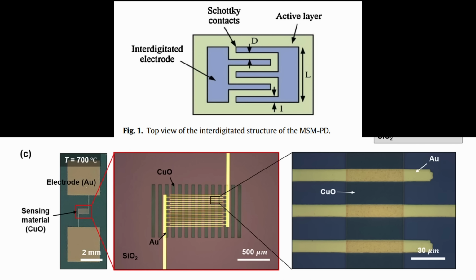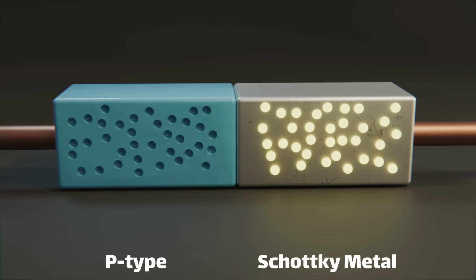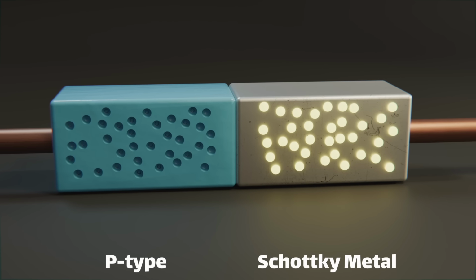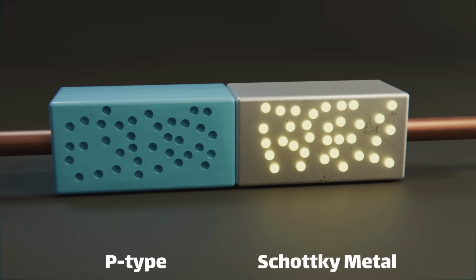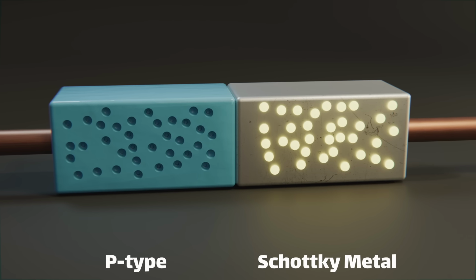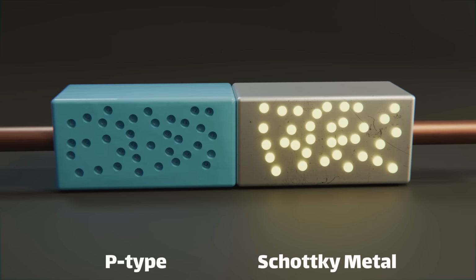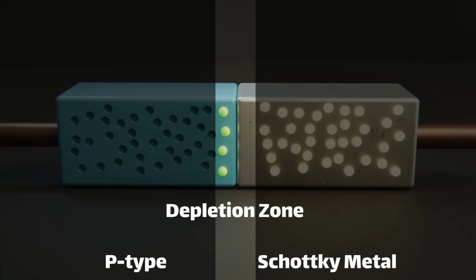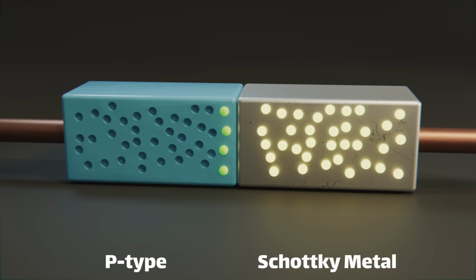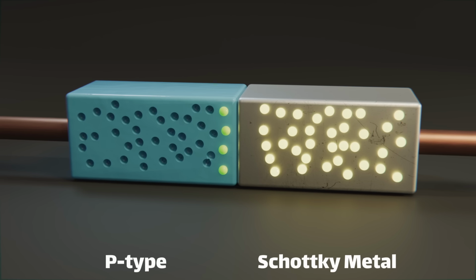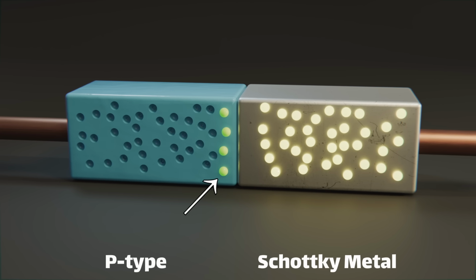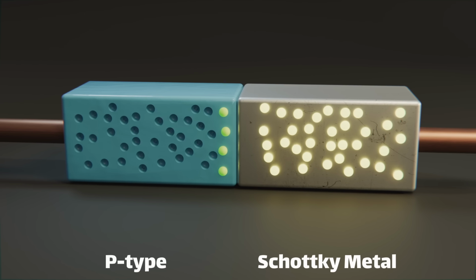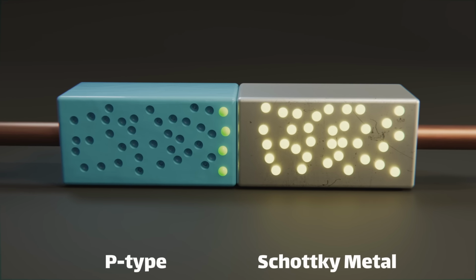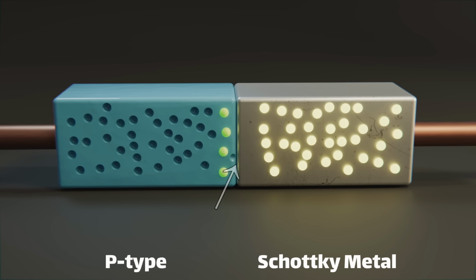And that's where the MSM device layout comes into play. Instead of using 2 different semiconducting materials, P and N, we pick a metal that forms a Schottky junction with the semiconductor. In this case, aluminum has the right work function for our needs, so we'll use that. The Schottky metal takes the place of an N-type semiconductor in our device. The mechanism is a little different, but it also forms a depletion region when biased, so the net result is basically the same. Electrons flow from the metal into our P-type semiconductor and fill up some of the holes, leaving behind charged ions. But because there are so many free electrons in the metal, when holes move in the opposite direction, they get swallowed up by the metal.